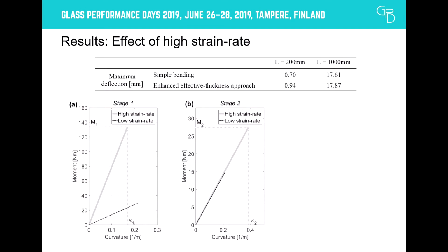In the second stage, the assumption that we previously made, that the contribution of the interlayer when we have only one glass fragment is negligible, is actually confirmed, as we can see that the two lines are parallel to each other. In the case of the high strain rates, we have assumed the transformation method, where both the unfractured glass layer works together with the interlayer, whereas for the case of low strain rates, we have assumed only the unfractured glass layer to behave on its own. The enhancement of the moment capacity is entirely due to the higher fracture strength of glass under higher strain rates, as discussed earlier on in the literature review.